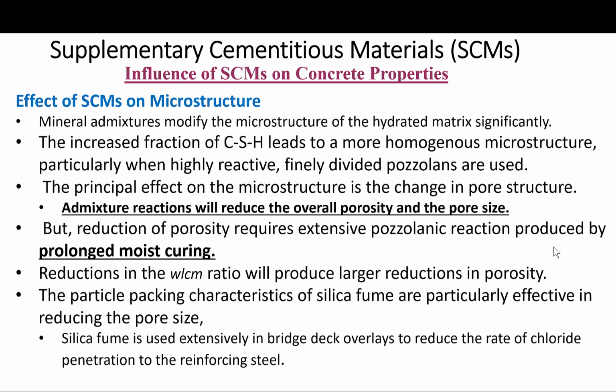However, a reduction of porosity requires extensive pozzolanic reaction produced by prolonged moist curing. Again, we go back to the practices in the field - moist curing is key in this case. Also, reductions in the overall water cement ratio will produce larger reductions in porosity. If you remember, when we use some of these mineral admixtures, we reduce the water demand because we get better workability, so the reduction in the water to cementitious materials ratio also plays a role in reducing porosity.